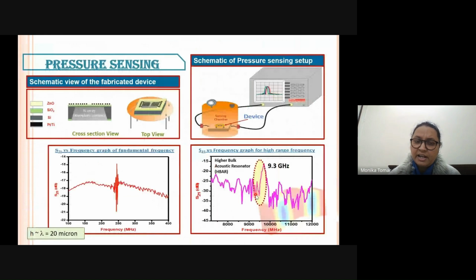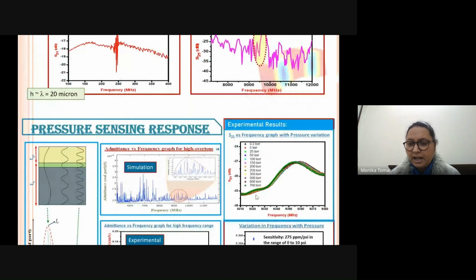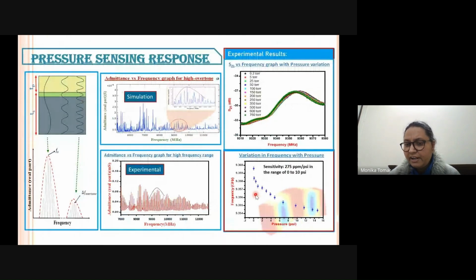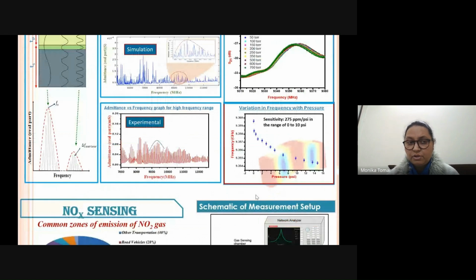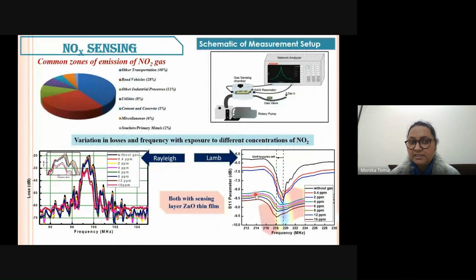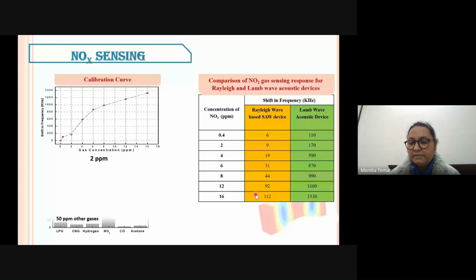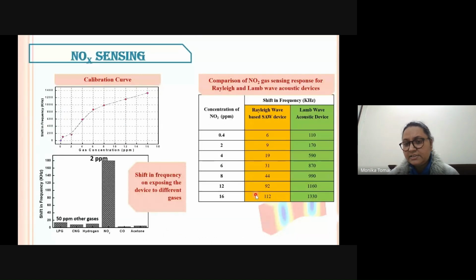Then the fabricated devices were utilized for low pressure sensing, and we got a very high sensitivity of around 275 ppm per psi in the range of 0 to 10 psi. The important thing is these devices are not available in the market, and we have to work on this. Then we utilize these devices for NOx sensing also, and when we compare them with the Rayleigh wave based devices, the sensitivity is about 2 orders higher.